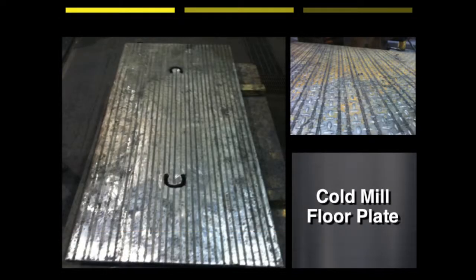Let's go back in time to when this all began. We first got involved in the aluminum industry by coating large pit covers in front of the cold mill. The standard operating procedure before that was textured grit paint. The problem with the paint is that the coolant would continuously get underneath the paint and loosen it. It had to be completely stripped and reapplied nearly every outage. To solve this problem, we applied a coarse grit stellite-based ESD coating to the covers. The solution was effective because the coating gets a true metallurgical bond. This was really important because there was a lot of forklift traffic here and a lot of scrap bin placements that were just dropped about.